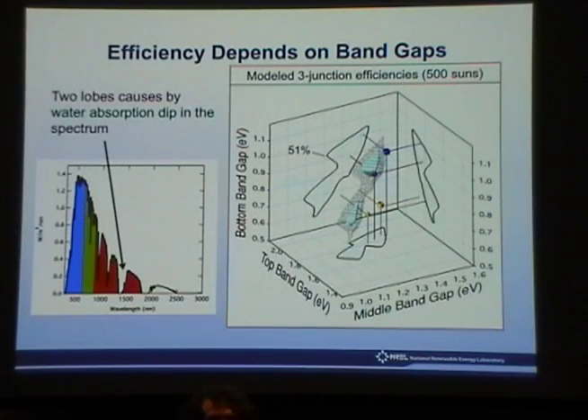Now the efficiency depends on the band gap, and this comes back to your question. So this is a model of the total efficiency of a 3-junction device at 500 suns. It's a function of the band gaps, top, middle, bottom. These lobes are supposed to be 3-dimensional contours, and then we've projected onto the 3 planes the 2-dimensional contours at 51 and 52%. There are 2 lobes to the graph because if you look at this plot on the left, there's actually a water absorption dip at about 1,400 nanometers. Depending on whether you put the bottom cell band gap above or below that water gap, you'll get either the high lobe or the low lobe.